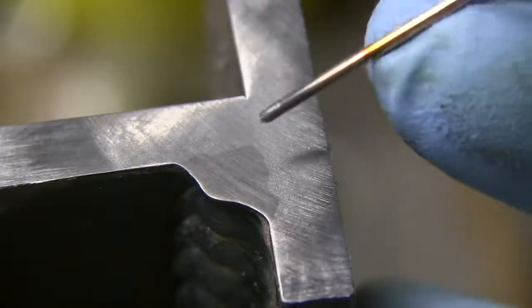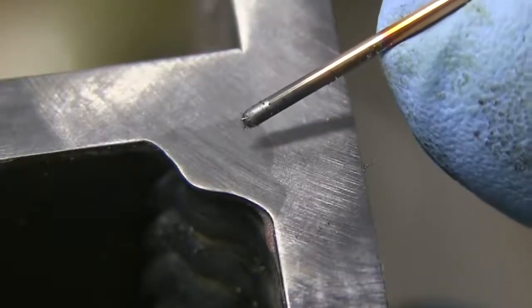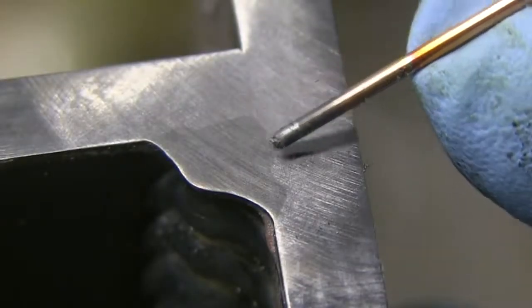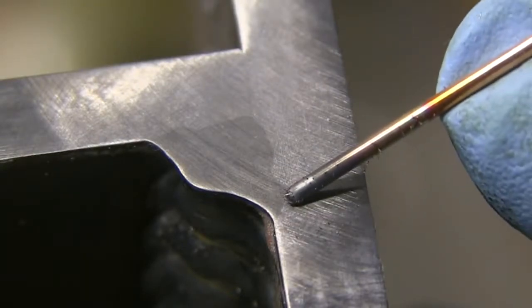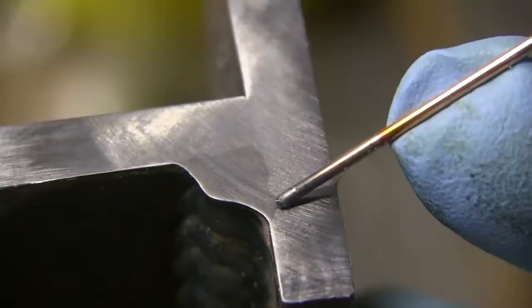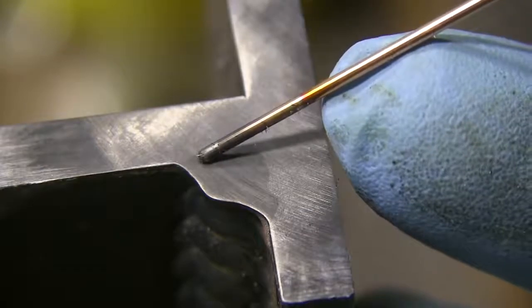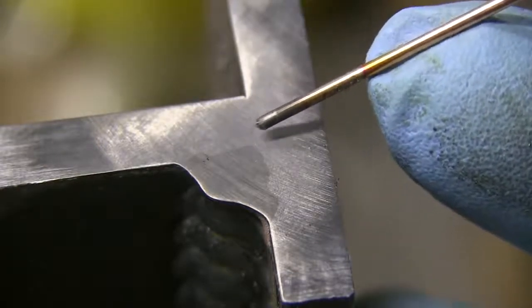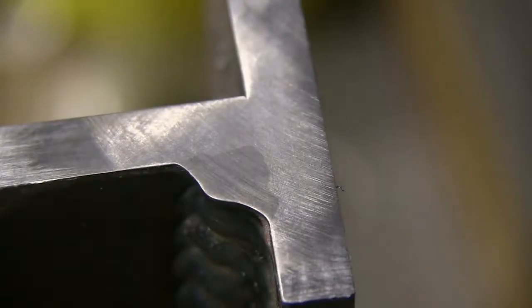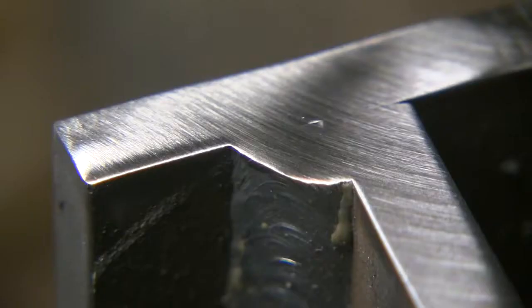The weld nugget looks a little irregular, but it's in there. It punched in all the way to the root of the joint. Got some pretty decent depth of penetration. Right there on the toes where I paused, it penetrated a little bit deeper. That's typical when you're tracing the puddle like a three-point technique, where you're going into the root of the joint and then bouncing from side to side. So, at those low settings, not too bad.